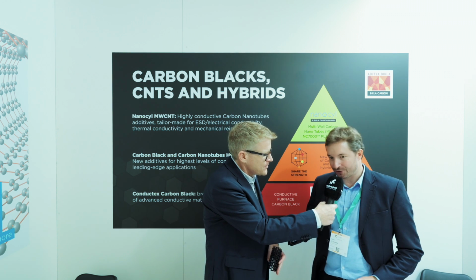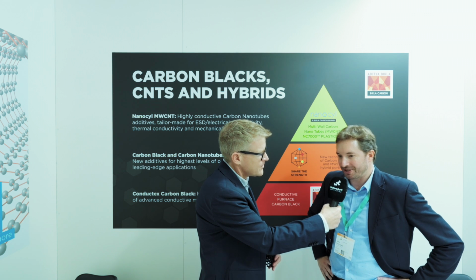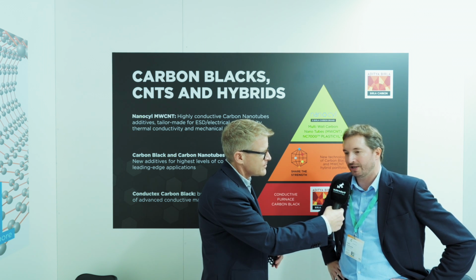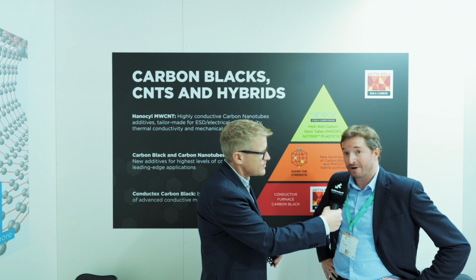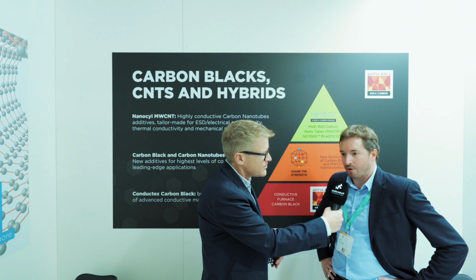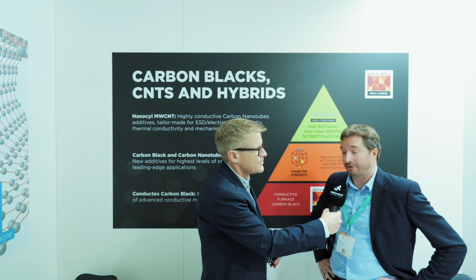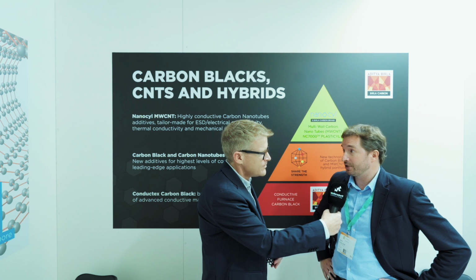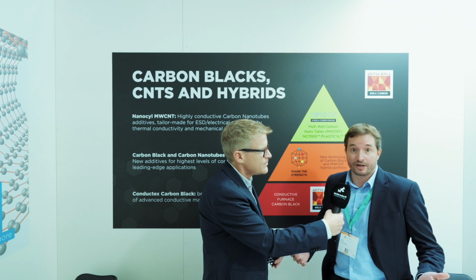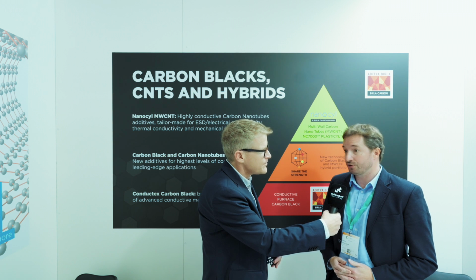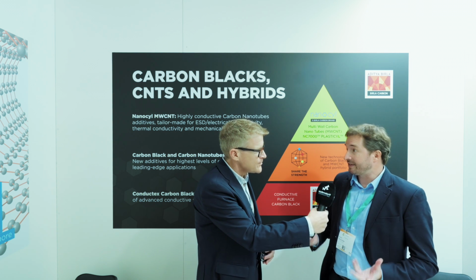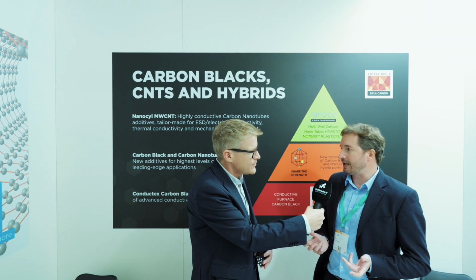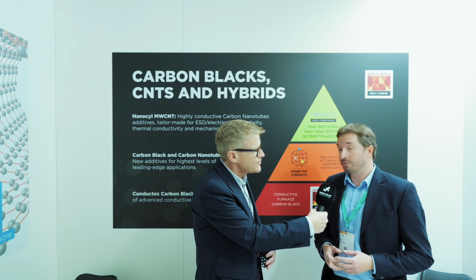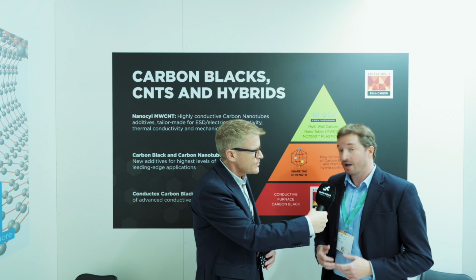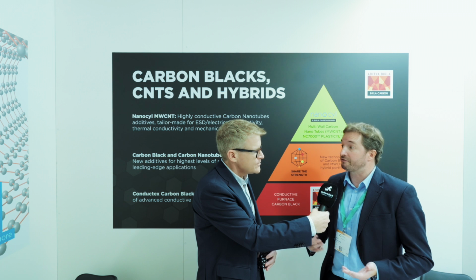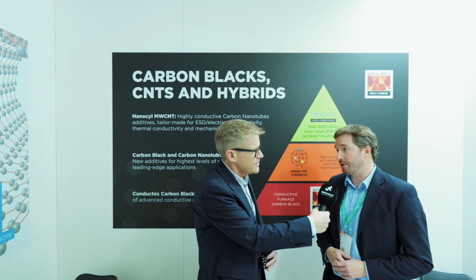So, carbon nanotube is an extraordinary material in terms of intrinsic properties. We are talking about a material more conductive than copper, 4 times more mechanically resistant than steel at a quarter of the specific weight, and also more thermally conductive than diamond, the most thermally conductive natural material known today. So we are talking about an extraordinary material at the particle level. Then we are incorporating this carbon nanotube into different kinds of matrix to increase their properties, typically providing electrical conductivity with a very low amount of filler, which is one of the main things carbon nanotube do today.